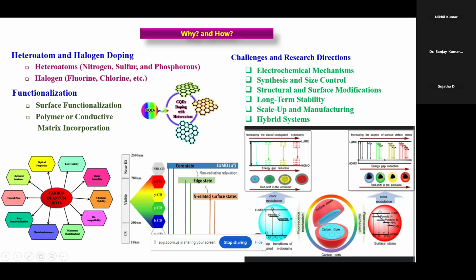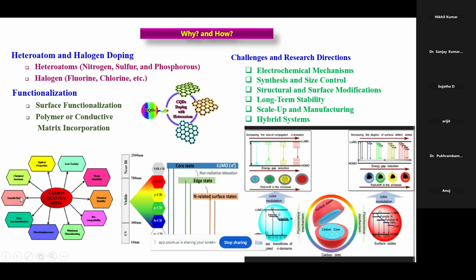According to this doping, depending on the heteroatoms present in it, the luminescence properties differ from one another. These carbon quantum dots have optical properties, low toxicity, water solubility, photoluminescence, tunable size and biocompatibility. Here we can see the UV range to visible and near NIR. In the visible region, around 450 nanometers we can obtain the blue emission of CQD, then 500 green, yellow, then red around 700, where we can observe the red CQD.